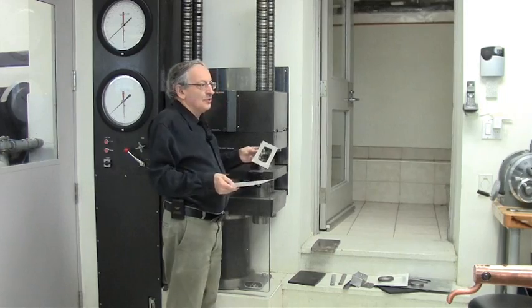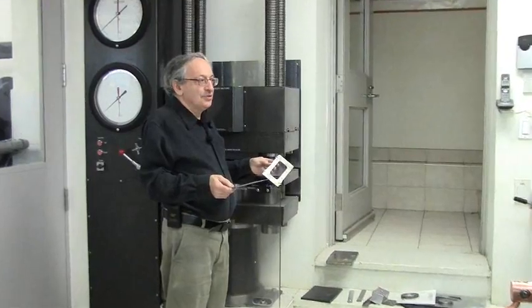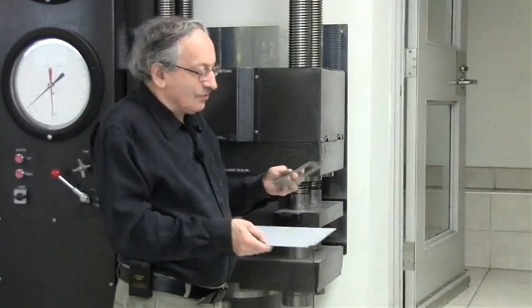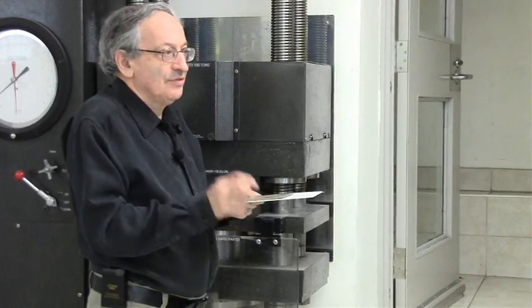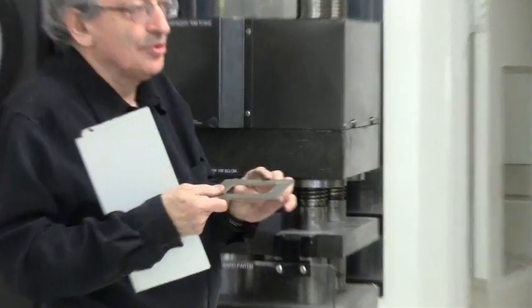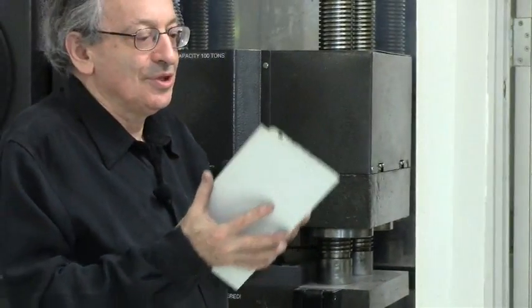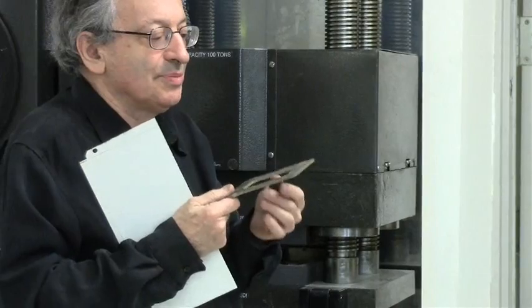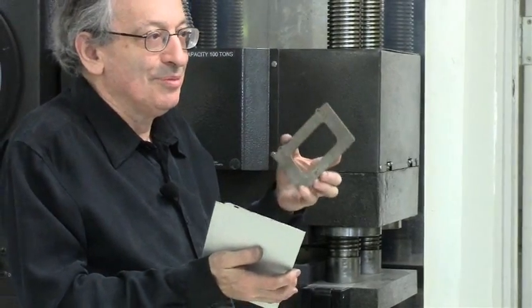So as I said, if you want to press it in one step with sharp detail, you have to press it into lead. And the lead can be reused by melting it again. So if I wanted to press this shape into this, I would just put a sheet of lead, maybe half inch thick under it. Now you have to be a bit careful, because if this is steel and has sharp corners, these corners are not rounded, it may actually shear. Because there's no big difference between a shear and a press. If I wanted to shear it out, I would make this part hardened with sharp corners. I would press it into rubber or lead and actually punch out the part. Which is also useful if you want many, many parts.